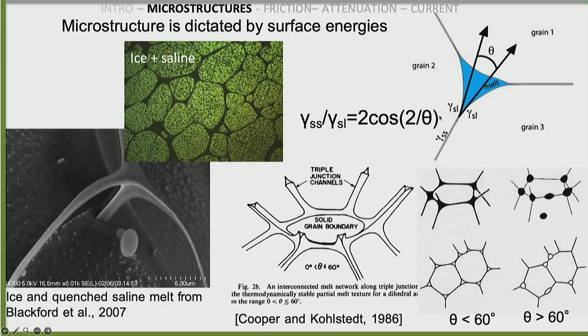And you can characterize this with this property called the dihedral angle. This dihedral angle is important because for materials with less than 60 degrees, the melt is considered fully mobile. It's in these triple junctions, and it can communicate through tubules. Whereas if it's over 60, it could get trapped as blebs, which probably wouldn't have any transport capabilities and might not really affect the mechanical behavior.